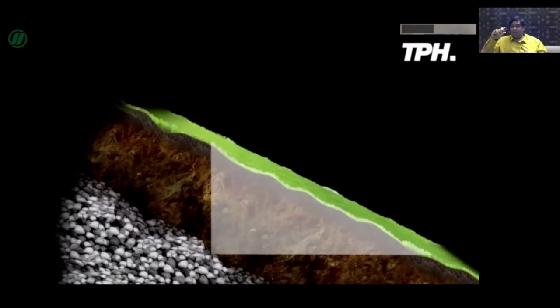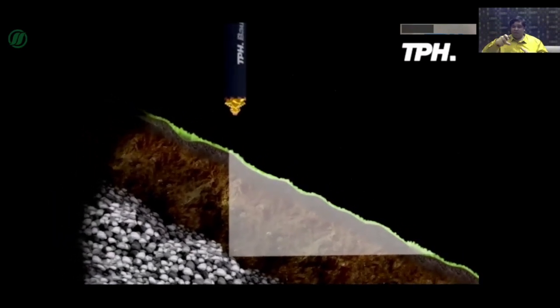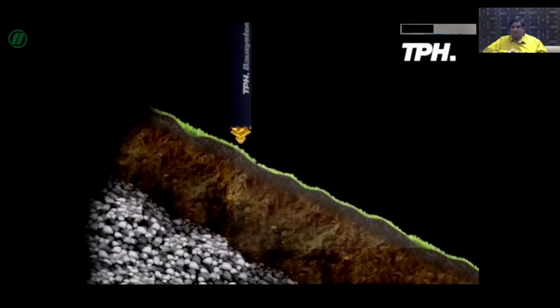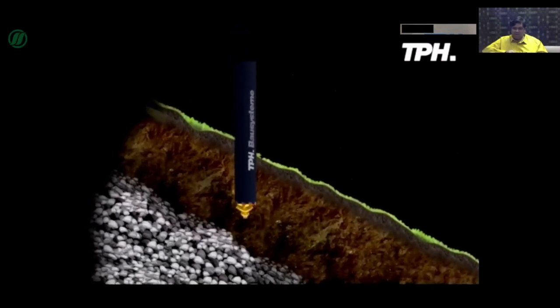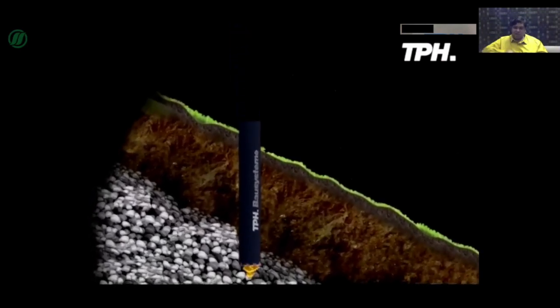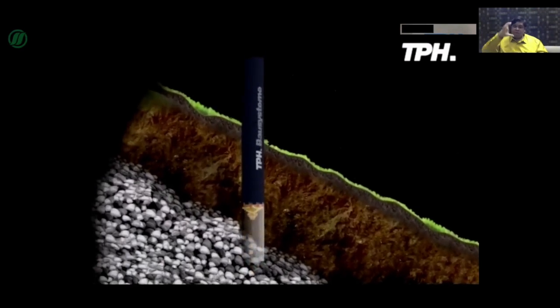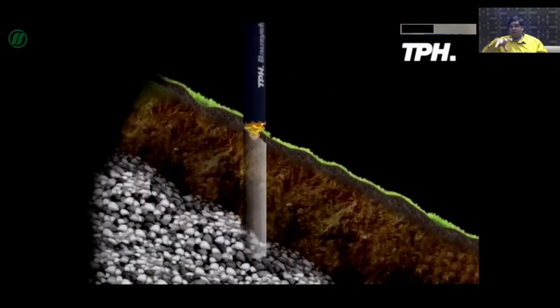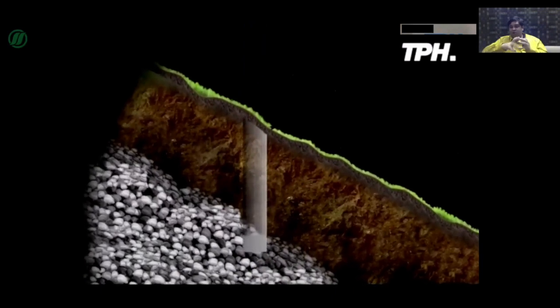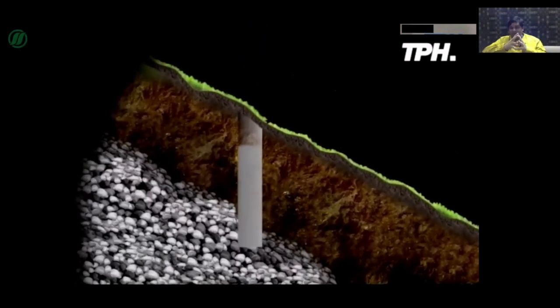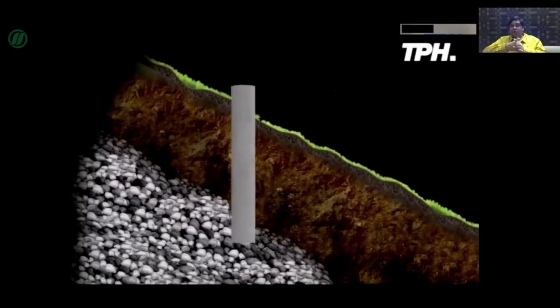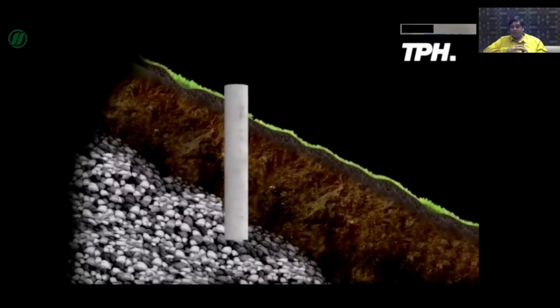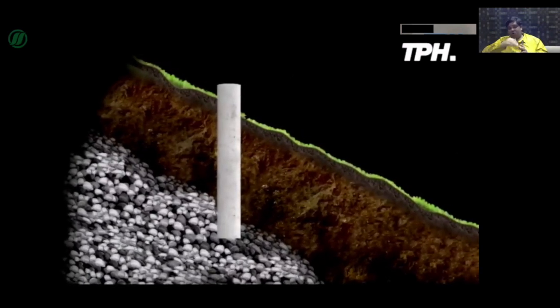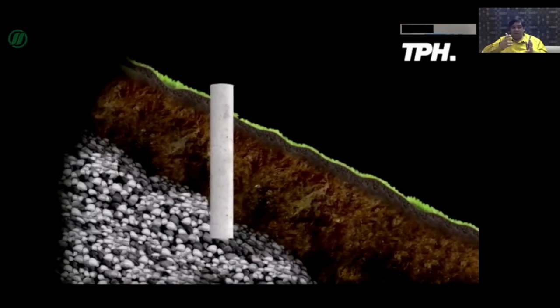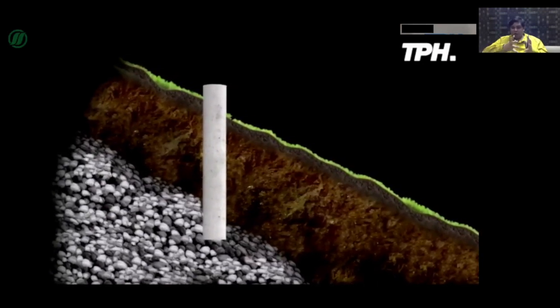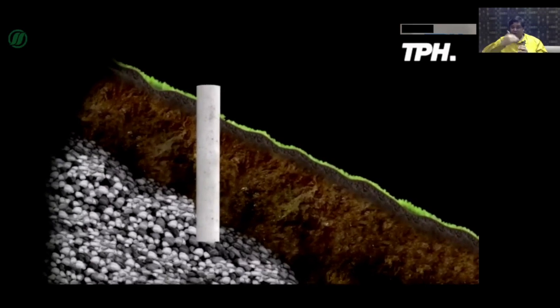And the best part of that kind of material is that this is just another case study with sheet piles. It follows the same technology. So I'll just let the video run. But the best part about using this kind of material is that once it holds and consolidates, the final strength of your consolidated mass also increases quite a bit. So you can get strength of almost up to 20, 30, 40 MPa. So it's pretty strong to bear a lot of load.